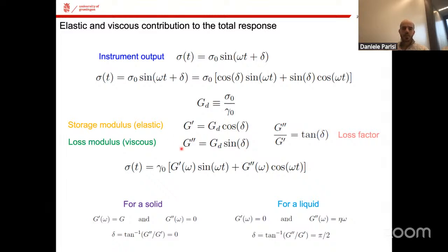So it goes without saying that if G prime is higher than G double prime, so the elastic contribution overcomes the viscous one, the material is behaving like a viscoelastic solid. And the other way around, if G double prime is higher than G prime, so the viscous contribution is dominating over the elastic contribution. So this is just a way that the rheometer uses in order to understand whether a material is a viscoelastic liquid or a viscoelastic solid.